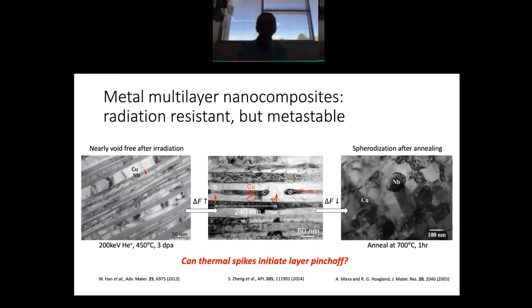not diffuse at all. And the reason why they're so sharp is because copper and niobium are phase-separating metals. They're like water and oil, right? So if you look at the phase diagram, there are no compounds, no intermetallic compounds, negligible mutual solubility. These things do not want to mix, right? So the interfaces between them stay very sharp. On the other hand, what that means is that the lowest energy state, the thermodynamically stable state of this composite, is just a block of copper on one side and a block of niobium on the other side with no interface, okay? So the interfaces in this composite actually create some excess energy.